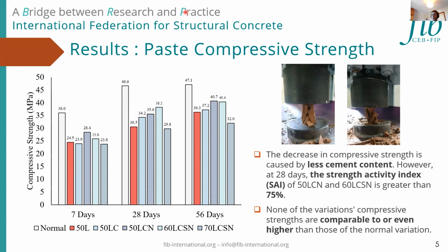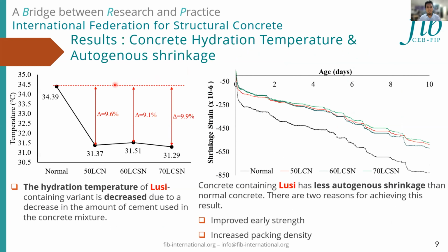I imagine the reduced hydration temperature could be helpful sometimes as well in cases where early thermal cracking is a problem or a risk. Yeah, the hydration temperature shows that Lusi decreases the peak of the hydration temperature by about 9% to 10% compared to the normal variation. It is good to use it in mass concrete, such as a raft condition, or a foundation, or the pillar of a big bridge.